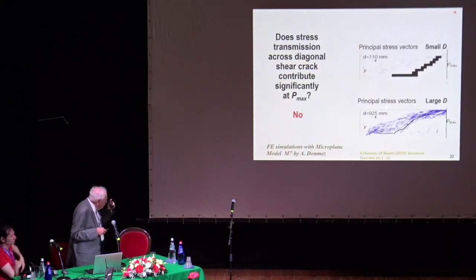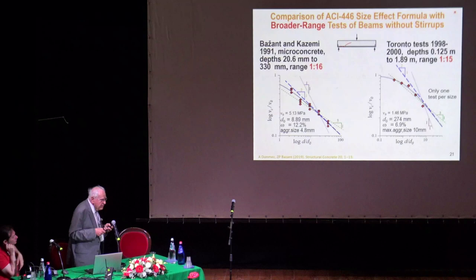Now, if we plot, for example, the principal stress vectors in compression, the tensile was negligible here, and they are all parallel to the crack. So it is not a fracture failure due to the main crack, but due to a secondary crack coming here. So interestingly, in the European code, this argument is ignored. They have failure based on strain.